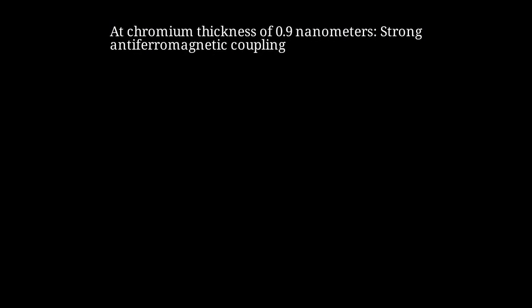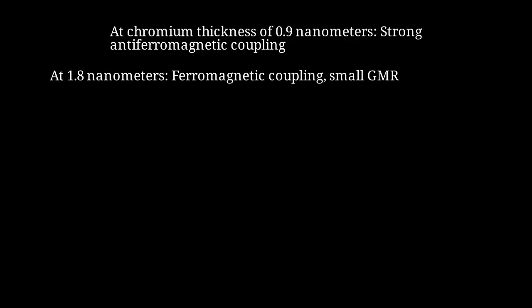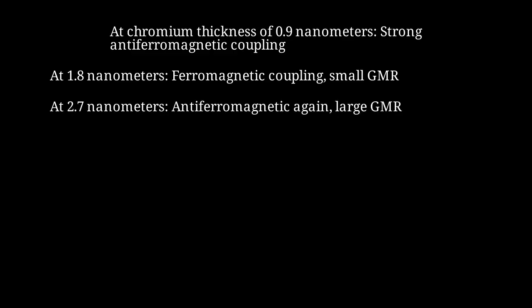GMR. At a chromium thickness of 0.9 nanometers, there is strong antiferromagnetic coupling. The layers naturally align antiparallel at zero field, giving high resistance. At 1.8 nanometers, the coupling switches to ferromagnetic due to RKKY oscillations. Now the layers align parallel at zero field, and GMR is small. At 2.7 nanometers, it switches back to antiferromagnetic, and GMR reappears. This oscillation with period roughly 1 nanometer matches the RKKY theory perfectly.